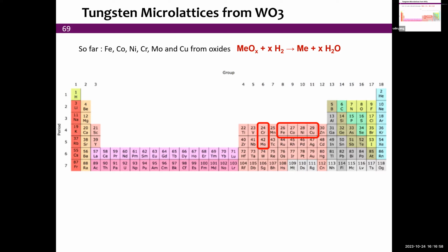So 10 minutes, fantastic. So far we've really talked about iron, cobalt, nickel, and chromium, and moly we did as well, but what about some other oxides, in particular tungsten? Tungsten is really interesting. This is a high melting element, very hard to sinter if you start from powders. But nature is kind. Tungsten oxide is relatively unstable, so you can reduce it with hydrogen, just like we've done for the others, and end up with tungsten and steam, which means that we can create submicron tungsten particles that hopefully will sinter fast, just like I showed for the others.